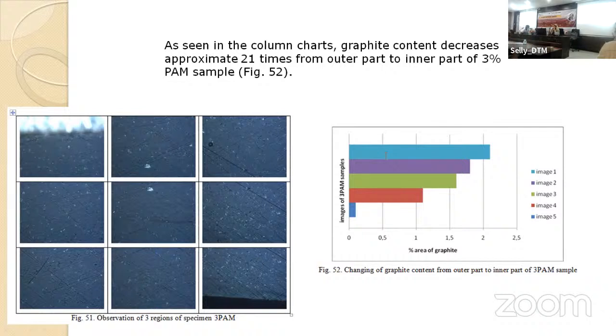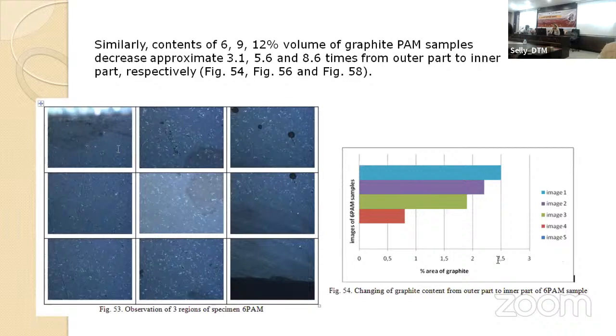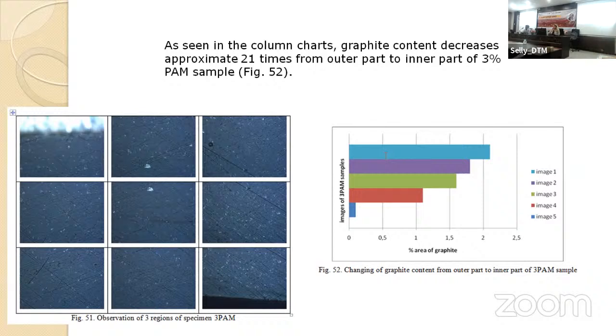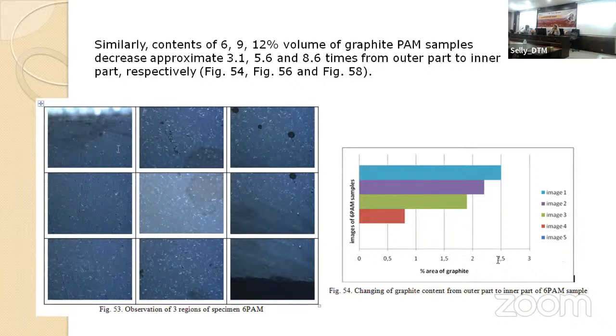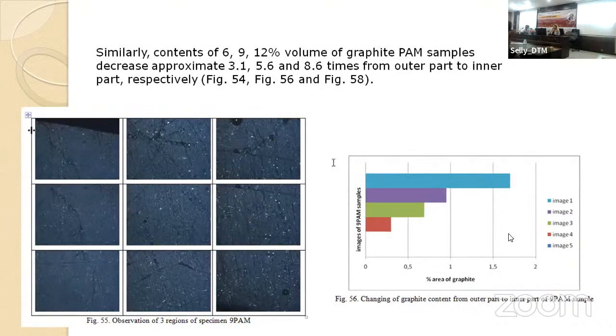We use a light microscope and an image processing program, and we detect all graphite according to the thickness. This is important for us because our sample has different properties of the material. You can see this figure belongs to the 3PAM sample, and this belongs to the 6PAM sample. And you can see it's hard to observe. It's not clear like a metal. Metal is simple, but polymer has some difficulties for observation and detecting of the size of the particle.